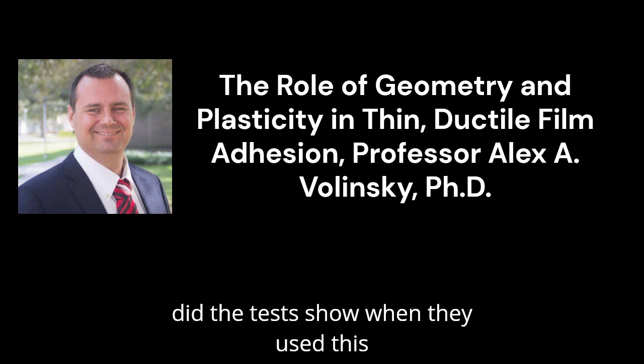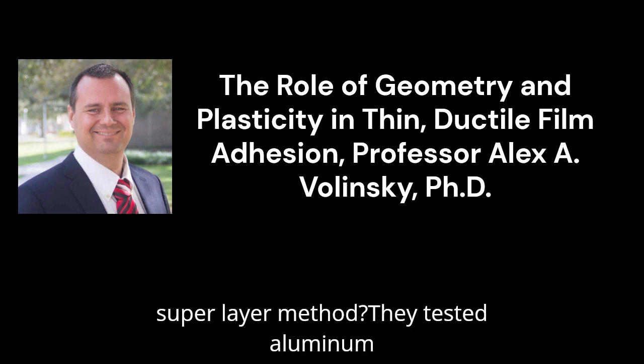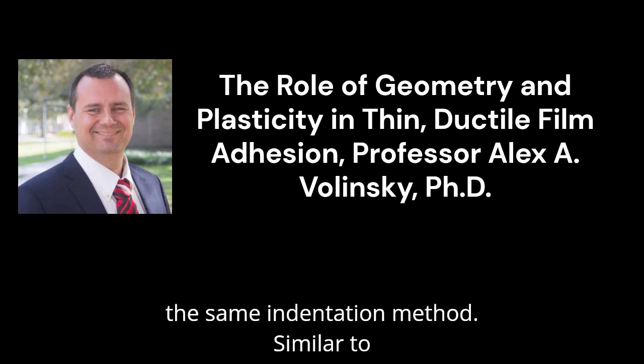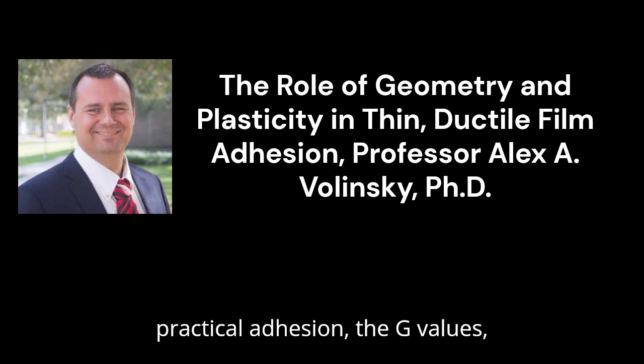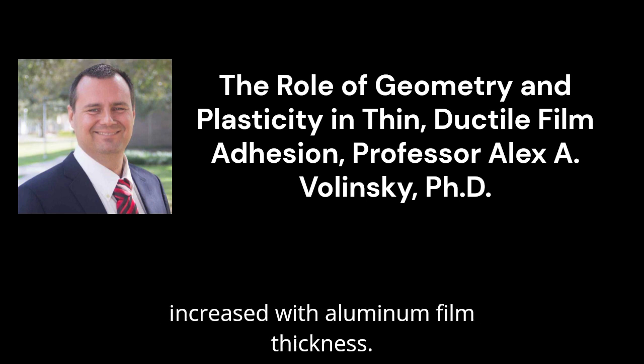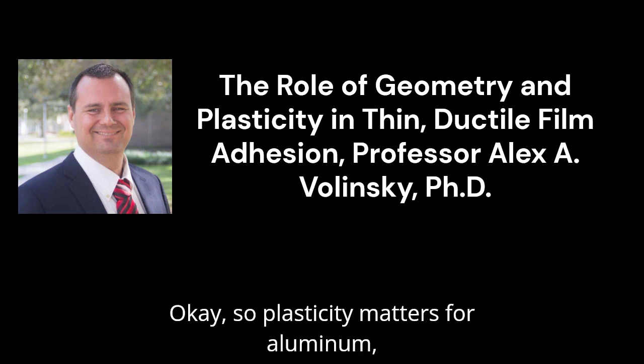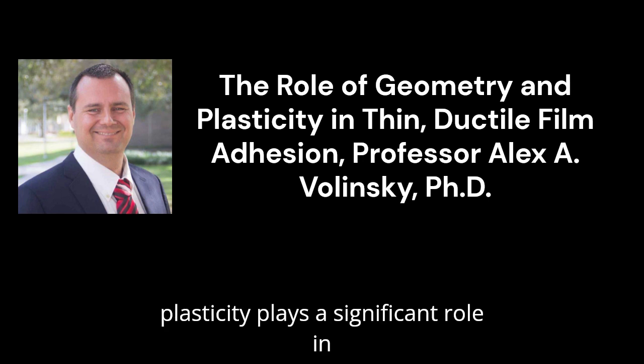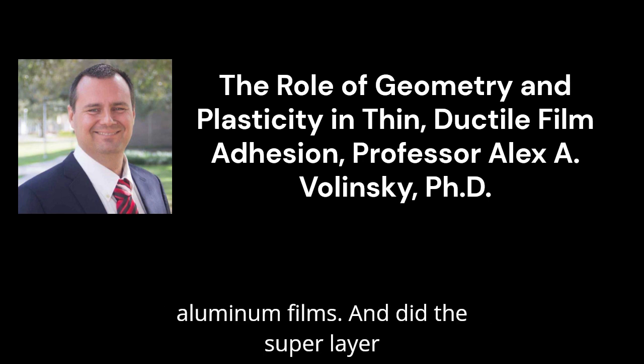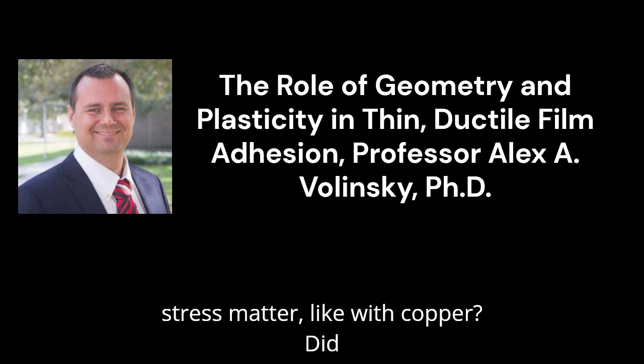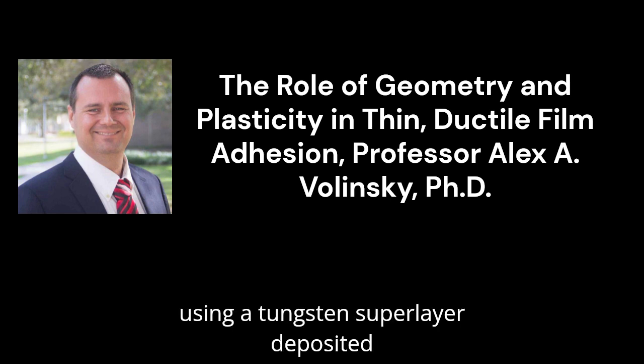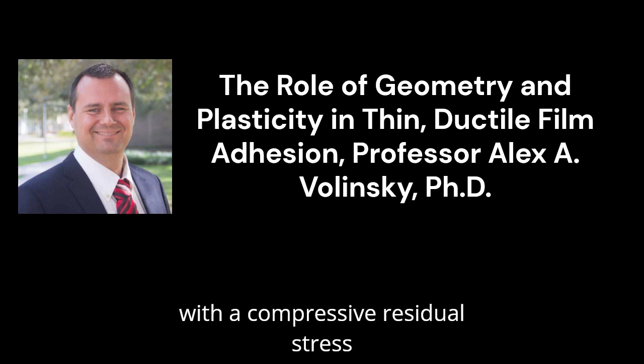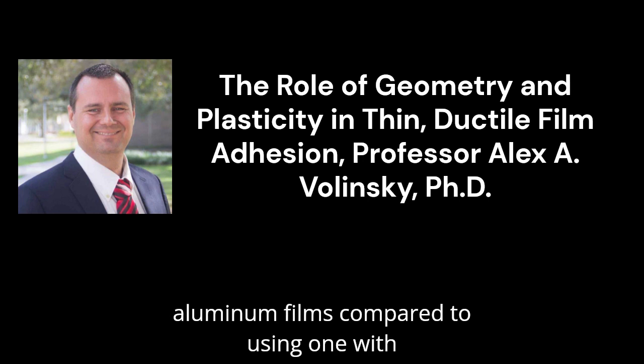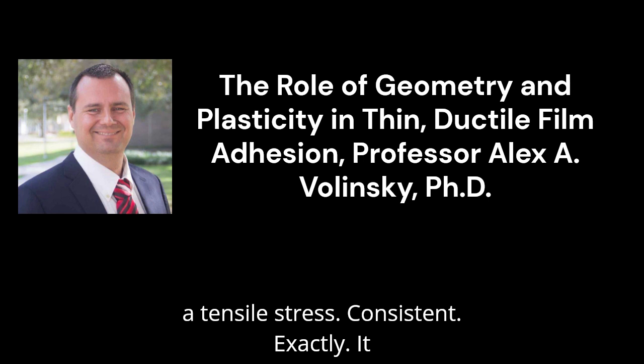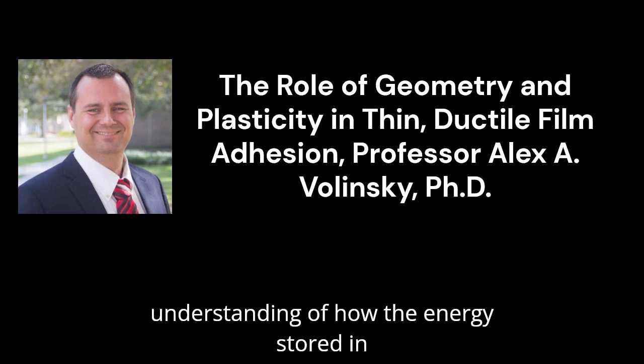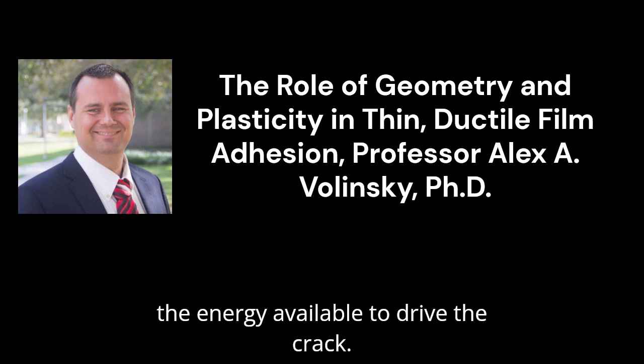What did the tests show when they used this superlayer method? They tested aluminum films with tungsten superlayers using the same indentation method. Similar to copper, they found that the measured practical adhesion, the G values, increased with aluminum film thickness. Okay, so plasticity matters for aluminum too. Definitely. Again, evidence that plasticity plays a significant role in the practical toughness of ductile aluminum films. And did the superlayer stress matter, like with copper? Did compressive stress help? Yes. They showed that using a tungsten superlayer deposited with a compressive residual stress resulted in higher measured G values for aluminum films compared to using one with a tensile stress. Consistent. Exactly. It aligns perfectly with the theoretical understanding of how the energy stored in the film superlayer stack contributes to the energy available to drive the crack.